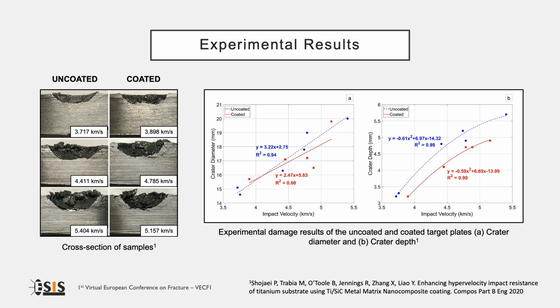In particular, the crater diameter was fitted with a linear relationship, while a second-order polynomial was used for the crater depth. From these diagrams, it is possible to notice how the impact resistance of the coated specimen is higher, since the crater depth at the same impact velocity is lower.